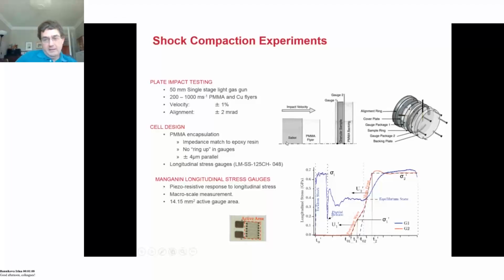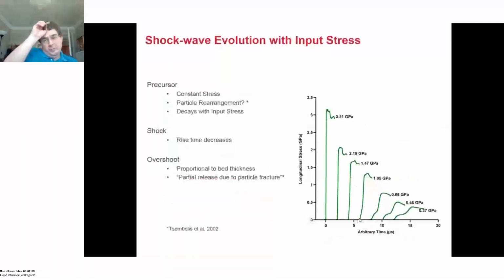And here we have a typical response of the system. Here is the front gauge, the loading pulse you see. You'll see some partial release due to reflection of the shock wave from the layer of granular material. And on the rear, you'll see a compaction wave, a precursor wave, followed by the main front. So you'll see this initial step function here. So we could follow this with particle size and grain size. And this is what we found.